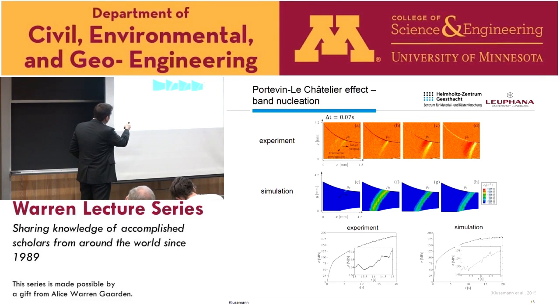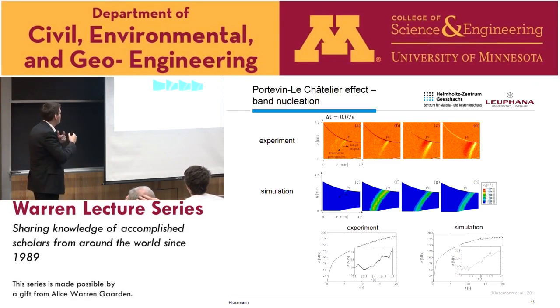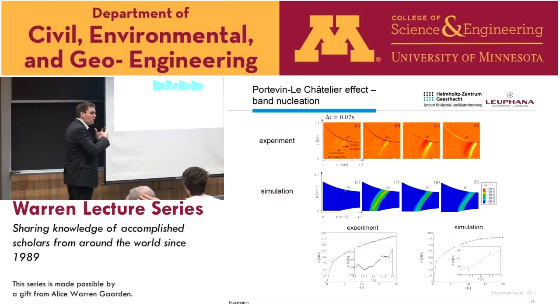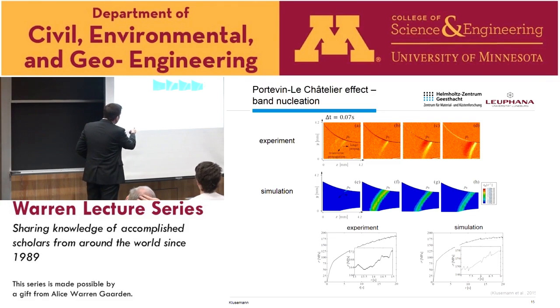And what you could see from the experiment very clearly was that during the transverse propagation, we already have a kind of behavior with respect to the longitudinal direction. So the PLC band does not need to be completely formed; it already starts to move inside of the sample. And we saw something similar here.